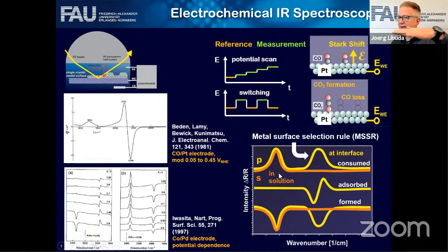For the s-polarized light, there's no electric field at the surface. The s-polarized field will be screened by the surface. So that means that for the s-polarized light, you will not have any absorption for species that are adsorbed on the surface. Whereas for the p-polarized light, you can have absorption at the surface and in the electrolyte. This is the so-called metal surface selection rule. And that's the way to differentiate between species that are in the electrolyte and at the surface. So for p-polarized light, you see the species in solution and at the interface, and for s-polarized light, you see the species in solution only. Sorry for the mistake a minute ago.